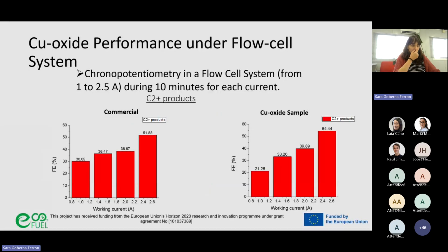Now, this slide focuses mainly on the C2 plus products. In both cases, the Faraday efficiency for C2 plus products increases, again, with increasing the current. And importantly, our copper oxide sample shows comparable or even higher C2 plus selectivity at the highest current density compared to the commercial sample. So this demonstrates that this material performs very well under practical flow cell conditions. This material was scaled up by Monolithos. I think they will present after me, and then it was also tested in other more relevant electrochemical conditions for the CO₂ fuel system.